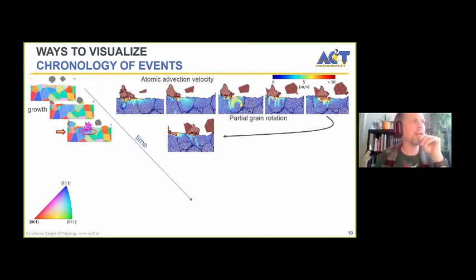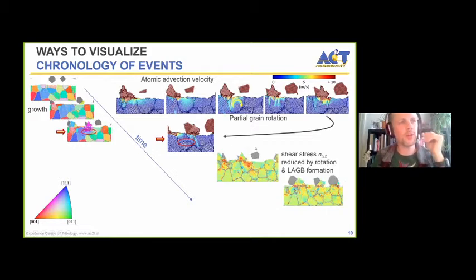And here we can see how the atoms within the grains start drifting. And actually here, this is where you see it. Here's a vortex forming that initiates this lattice rotation. And here's where it's finished. And this situation here is exactly the point that she's circled here. Then we also looked at the stress tensor component.